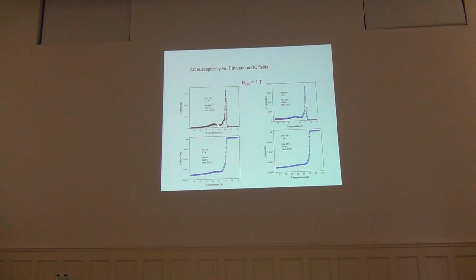Double peaks in the dissipation signal I have seen in my life, many of those. It happens if you have a multi-phase sample. It happens if you have a polycrystalline sample and you have an intergrain critical current and an intragrain critical current. So it was not very spectacular.